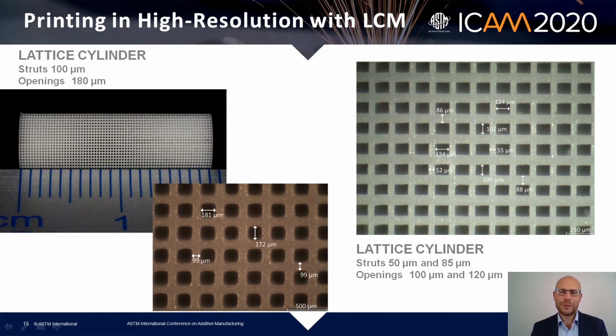And also interesting in terms of resolution, what can be achieved here. Here you see two different lattice cylinders. So we have struts of 100 microns or even below 100 microns, so 50 to 85 microns. One is in Z, the other one in Y direction. You can see that it's a very, very high resolution, and the openings are in the range of 100 microns. And you can also see here that this technology is very, very reproducible. So we can achieve really tight tolerances, and we see this technology already in industry, in serial production, and there you have to fulfill all those requirements, and especially reproducibility and tolerances are a very big topic there.